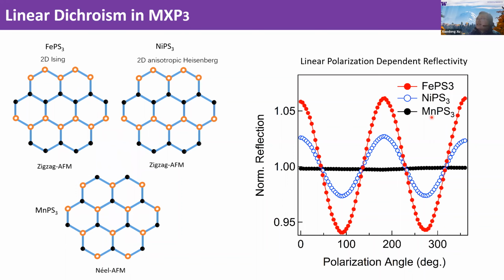So this is consistent with their magnetic order. For both iron phosphorus trisulfide and nickel phosphorus trisulfide, it's a zigzag antiferromagnetic order. So this zigzag antiferromagnetic order breaks the rotation symmetry and gives rise to these optical anisotropies. But for the manganese phosphorus trisulfide, it's a Néel order, so the three-fold rotation remains. That's why we don't have these optical anisotropies. So from a symmetry point of view, all the data is consistent with the magnetic orders.